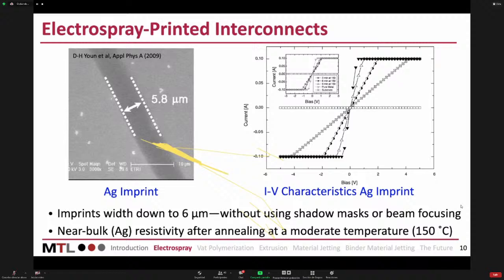So what you see here is that electrospray moved from being able to make complex pictures to actually make something useful. So right now, this is something that could be used for interconnects, or for routing signals to whatever electronics you have. And this is made at room temperature, except the part of the annealing of the film, of course. So this is really exciting. And again, it's just spraying these nanoparticles, and you can do these long and narrow features because you can operate it at close proximity, which is called near field electrospray.